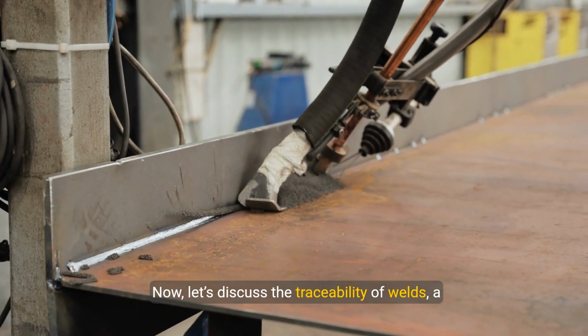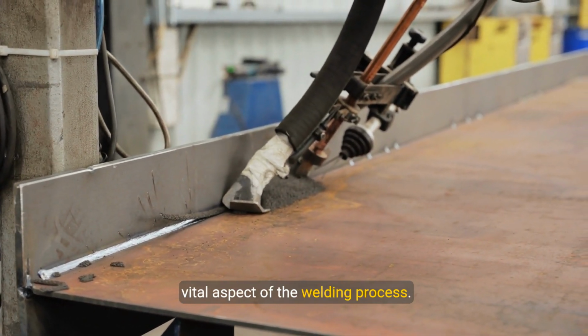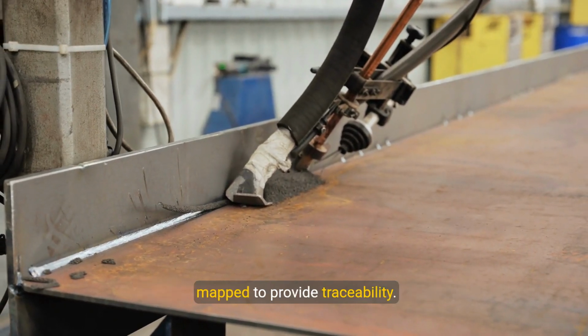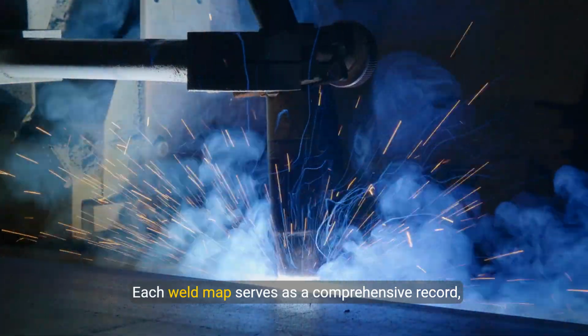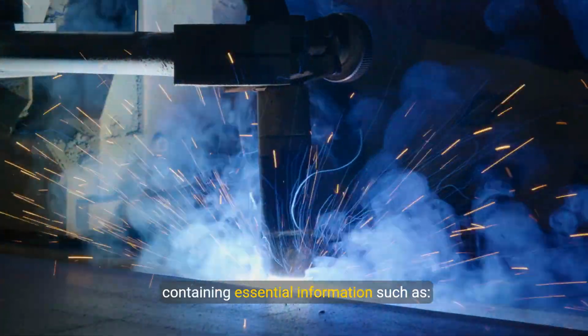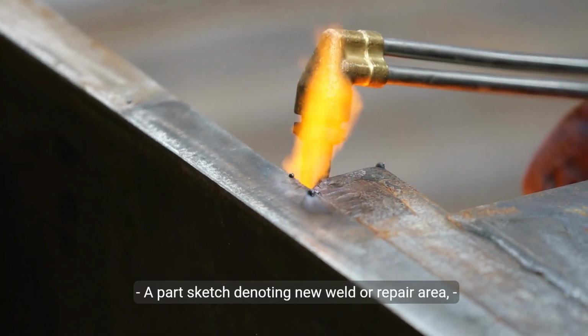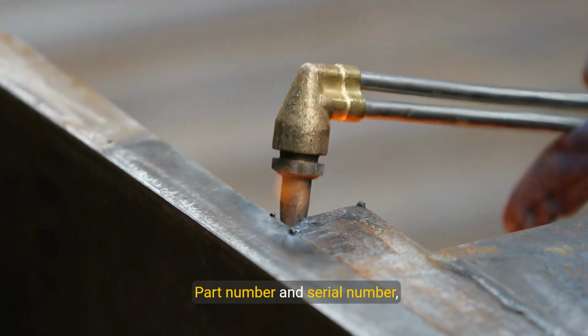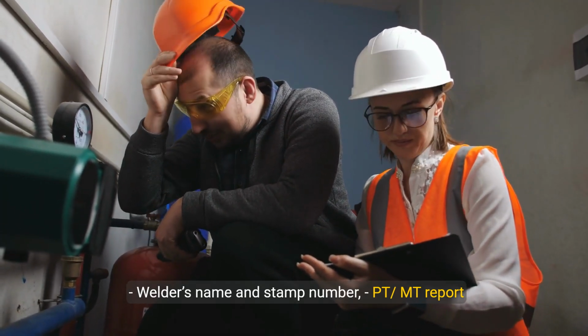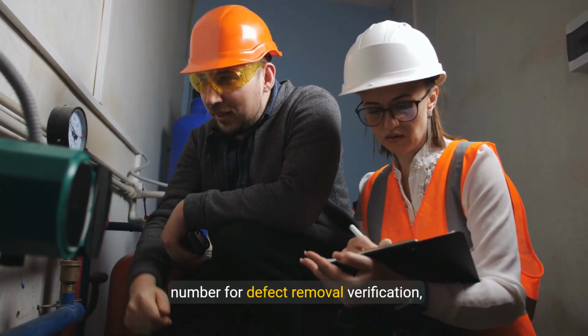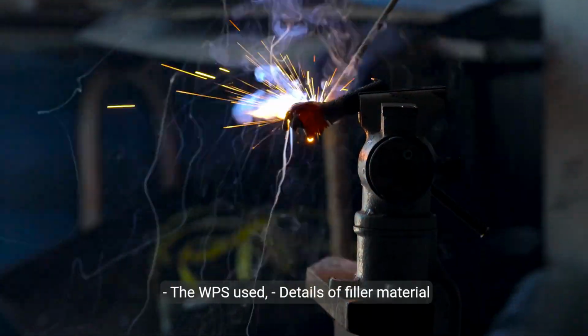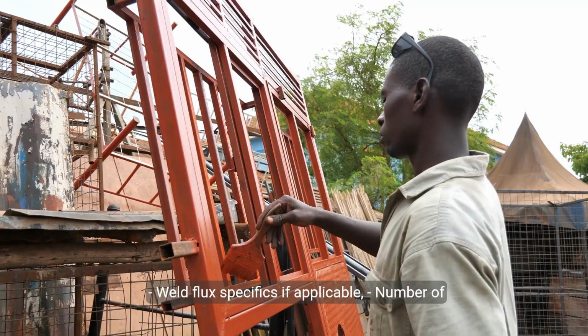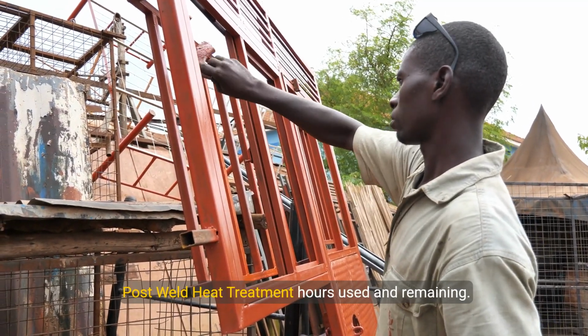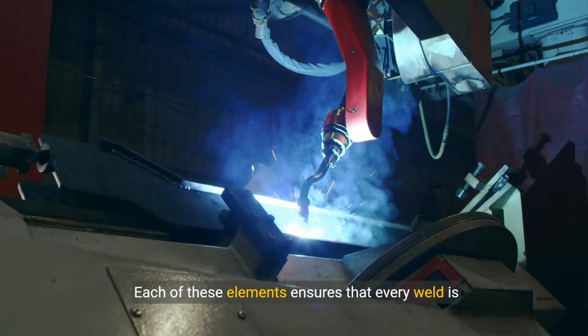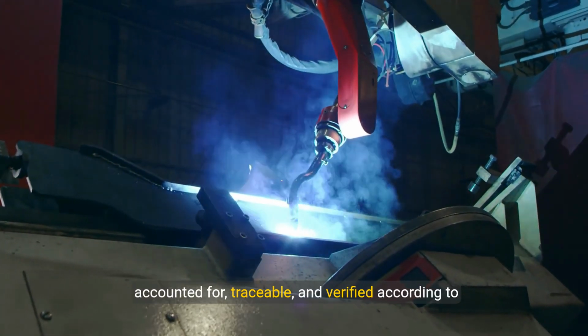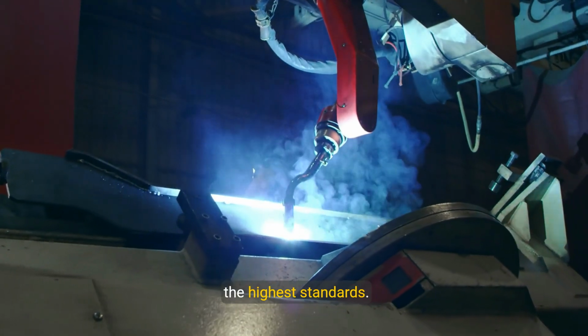Now let's discuss the traceability of welds, a vital aspect of the welding process. New welds and repair welds must be meticulously mapped to provide traceability. Each weld map serves as a comprehensive record containing essential information such as a part sketch denoting new weld or repair area, part number and serial number, welder's name and stamp number, PT/MT report number for defect removal verification, the WPS used, details of filler material including heat, batch, and lot, weld flux specifics if applicable, number of post-weld heat treatment hours used and remaining. Each of these elements ensures that every weld is accounted for, traceable, and verified according to the highest standards.